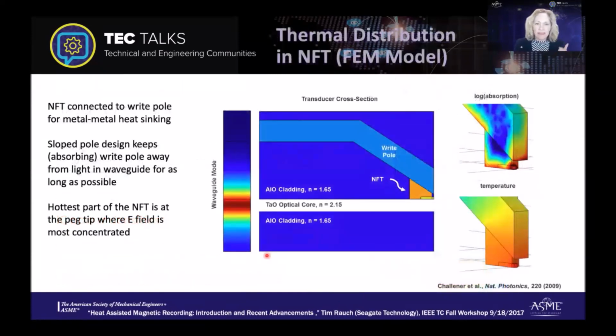And so first was just getting some of that heat out. We have the NFT, and the write pole and the rest of the writer is actually a very, very large piece of metal compared to the very small NFT. So the first thing is to thermally connect the near field transducer to the write pole with the heat sink. The other was to slope the pole and get it out of the way of the optical path, so we aren't getting much of that scattered unused light onto the write pole. Those two things made quite a bit of difference in improving the temperature distribution.